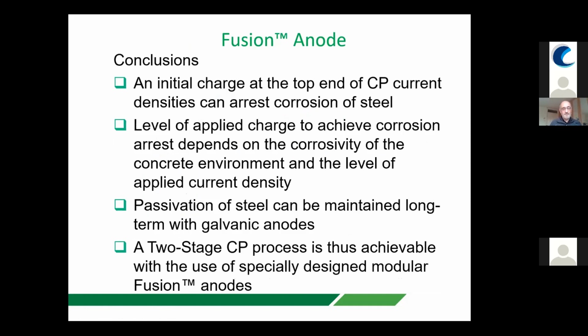So conclusions. An initial charge at the top end of the corrosion protection current density, i.e. a little bit more than 20 milliamps per meter squared. We tend to try and achieve about 30 milliamps per meter squared. This can arrest corrosion of the steel if you apply enough charge. The level of applied charge to arrest this corrosion depends on the corrosivity of the concrete environment, i.e. the level of chloride primarily. And subsequently passivation of the steel can be maintained long-term with the galvanic anodes.